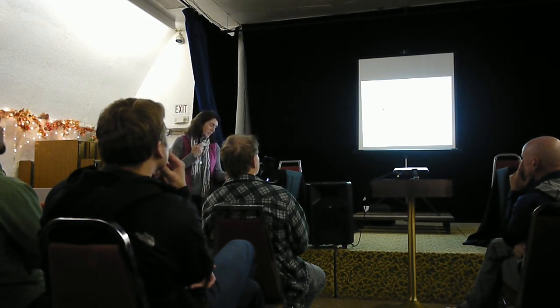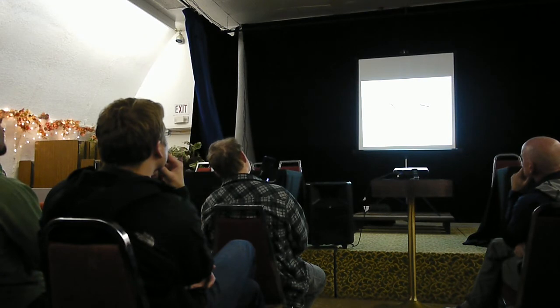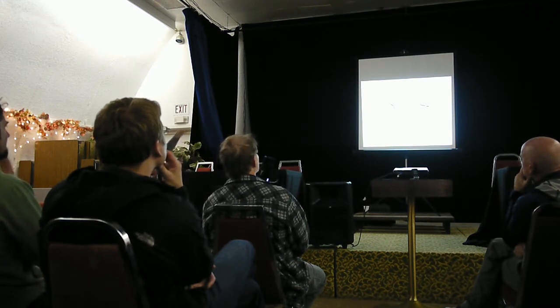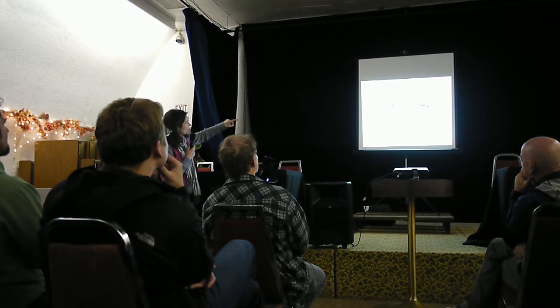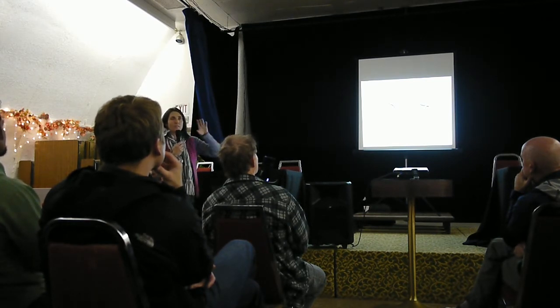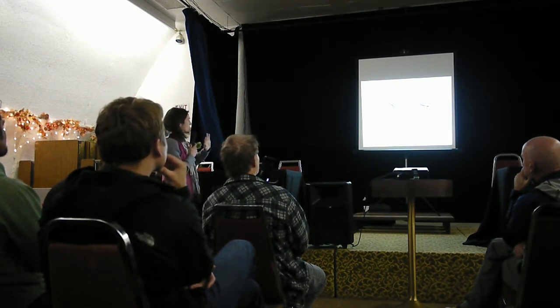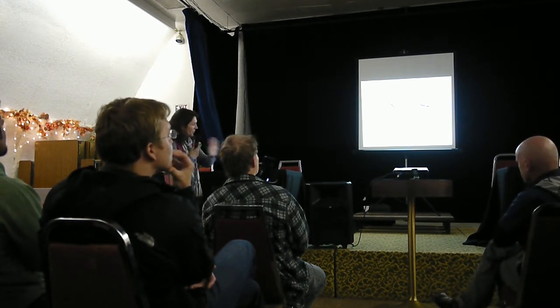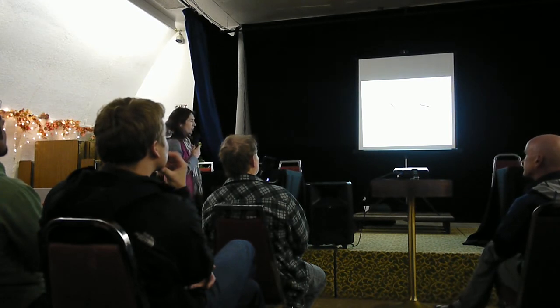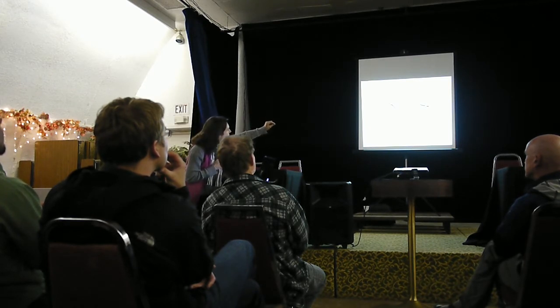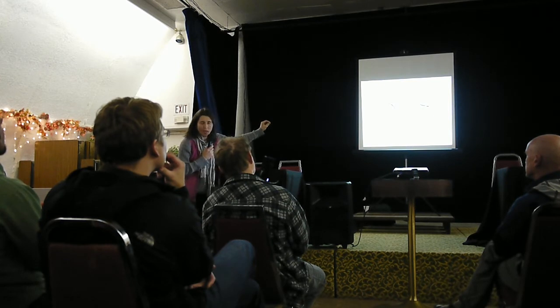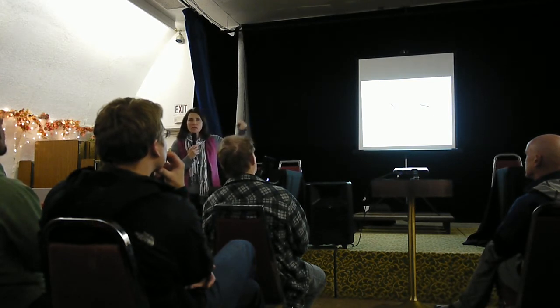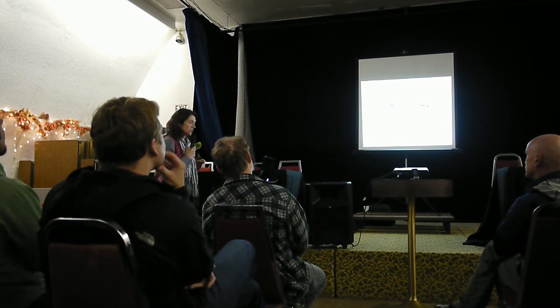And that's it there. So I put this under a microscope, and what you're looking at is just a fraction of the hanger and has cracks going everywhere, fine cracks going everywhere. It's over the entire hanger cross-section. I've never seen stress corrosion this bad. Like a pipeline would get excited about one tiny little crack that goes a third of the way down. That micrograph would freak out a pipeline company. So it was pretty incredible to see this.